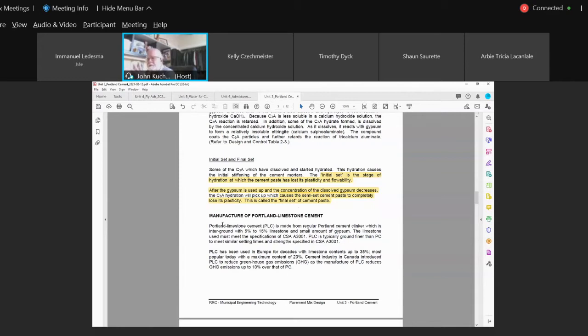And when you have typically 100% crushed limestone, it's rock flour, rock dust, if you want to call it. We were always getting fairly good strengths at Carsey in the previous labs, even though our minus 200 was excessive, it was possibly more limestone dust. And they found out now that if you take limestone rock flour, real fine crushed limestone, mix it with Portland cement, it actually gives you better strength.